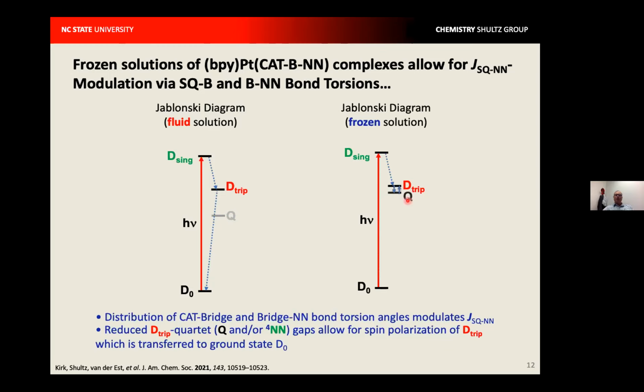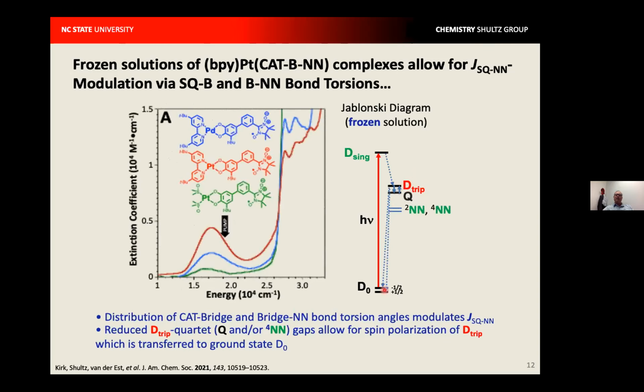And for spin polarization, this turns out to be key, because if within those conformations with weak exchange coupling, you can set up an equilibrium between D-trip and the quartet, you can spin polarize the M sub S levels of D-trip. And under the right circumstances, you can see spin selective decay to the ground state to transfer that spin polarization back down to the ground state.